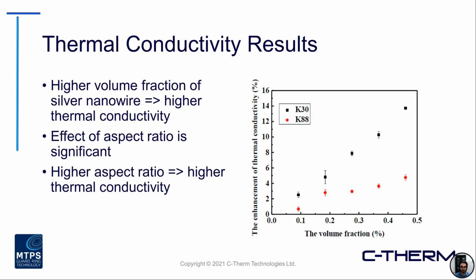So what they found from their results is essentially, as you would expect, the higher volume fraction led to a higher effective thermal conductivity measurement, so a greater enhancement of that thermal conductivity. But also the effect of the aspect ratio, or the size of that additive, was rather significant. They noted that the higher aspect ratio sample also had a generally higher thermal conductivity compared to the one that was lower. So even though it's the same material being added, size and shape can have a very drastic effect as well.